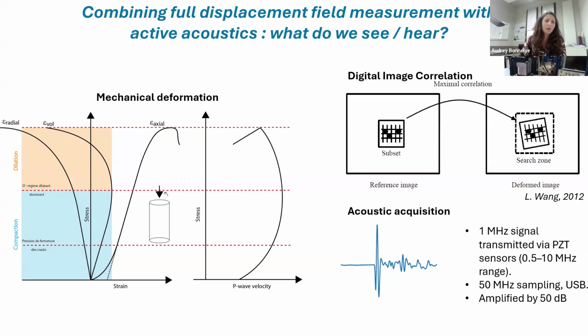or in our case, with an SEM. And what we are trying to do, and sort of succeeding in doing with Mathieu, is to combine the use of digital image correlation together with active acoustic acquisition in order to have a view of the full field of deformation, and try to combine it with something that we know happens and that we're used to measuring when we're doing rock mechanics, and also to be able to compare it with what people are trying to look at in the field. So the idea of all of that is to have a better insight on how you can localize deformation, what the different mechanisms are, and can we somehow quantify it both with full field deformation and acoustic acquisition.